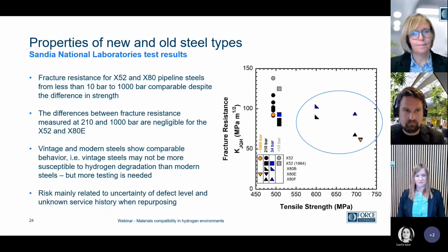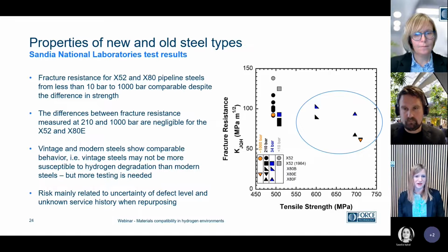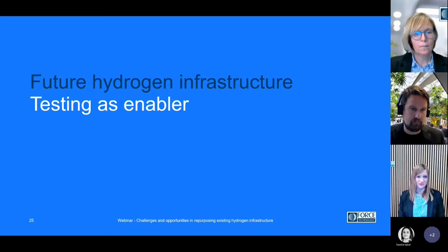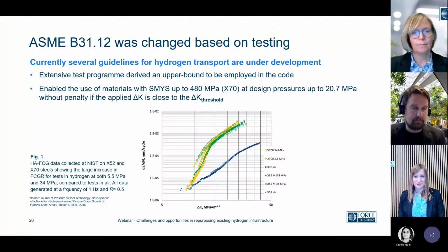Further, they also tested fracture resistance in vintage and X52 to X80 steel, so different strength classes. And I've encircled the X80 steels, showing that even though they have a much higher tensile strength, the fracture resistance is similar. And the squares are the vintage X52 compared to the modern X52. And again, it's not as distinctly different fracture resistance. It points to the risk in repurposing is mainly related to the uncertainty of defect level and that we don't know much about service history when repurposing. So that is a promising result. But more testing is needed because hydrogen embrittlement occurs at this critical combination of stress, material susceptibility, and hydrogen exposure, which we cannot put a limit on.